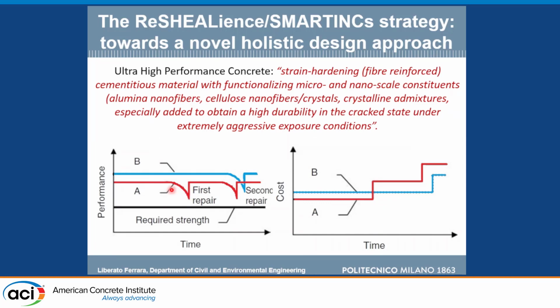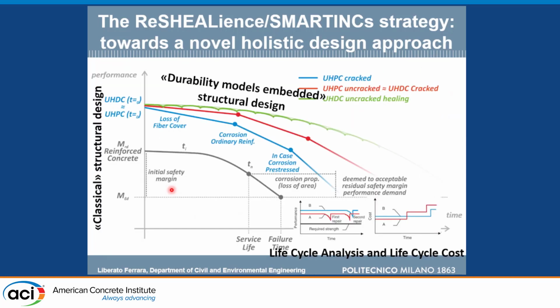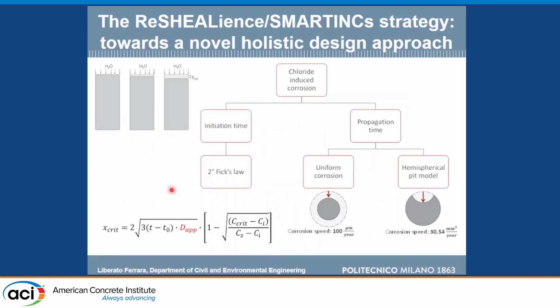So we performed the life cycle analysis, and what we wanted to see, let's try to see how the performance of the structural bending moment, for example, capacity, decreases over time because of the aggression or is maintained because of the self-healing. So we use a different kind of aggression mechanism for chlorides. The Fick's diffusion law governs the diffusion of the chlorides. When the chloride reaches critical content at the reinforcement, the corrosion starts, and depending on the scenario, you might have uniform corrosion or hemispherical pit corrosion.